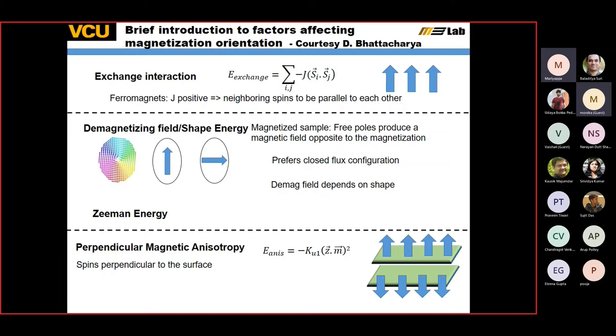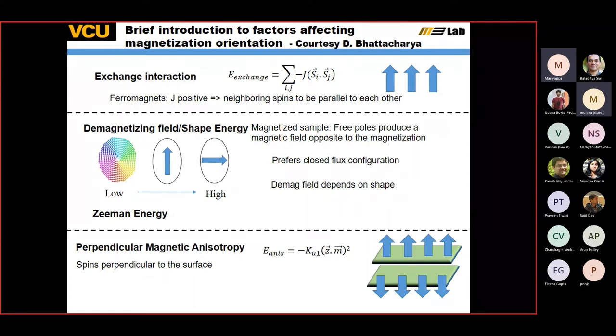The demagnetizing field or shape anisotropy determines that if you have a nanoscale magnet of elliptical shape and it is small enough, the magnetization will point along the long axis because the fringing fields make the short-axis configuration energetically unfavorable. If the magnet is big enough, say 300 nanometers, it might also form a vortex state where there is continuous rotation of the spins, which comes at a cost of exchange penalty. But the gain in demagnetization energy is sufficient to justify this.